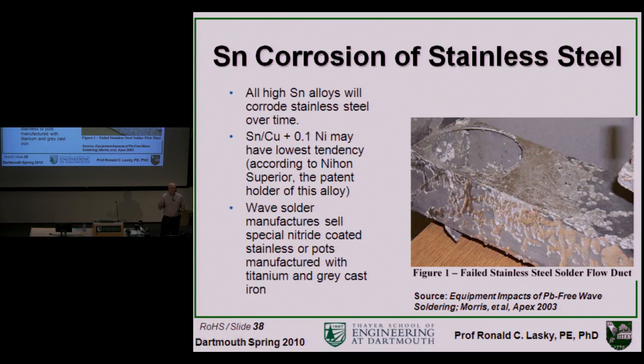And yet gold is something that we envision as being one of the most corrosion-resistant materials, but not necessarily to liquid metals. Well, stainless steel, which we consider to be corrosion-resistant, is strongly attacked by lead-free solder. One of the thermodynamic aspects of lead-free solder is that it's essentially 100% tin, with just a little bit of silver and copper, whereas leaded solder was a lot of lead, 37% lead. From a layman's perspective, tin is thermodynamically starved to digest or dissolve other metals. And so it tends to be more aggressive with copper, which is another problem that I can't go into because of lack of time, but also attacks stainless steel.